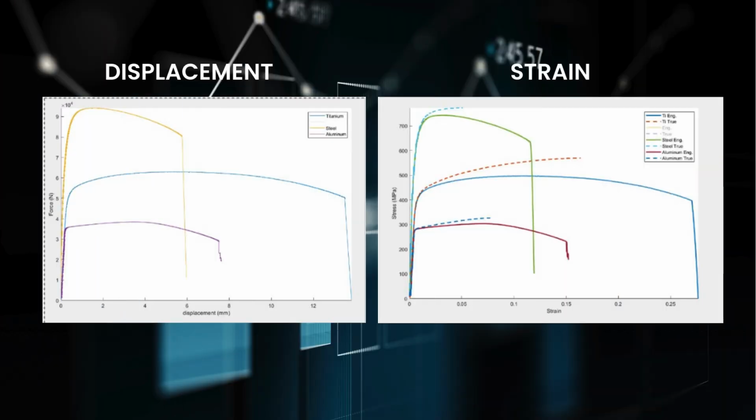Thank you, Sally. Chet Baker here to show off the graphs of the experiments conducted today. The most important one is the one on the right, the stress-strain graph. As you can see, the steel had the highest yield and ultimate tensile strength, actually being relatively close to each other. However, the elongation was just not up to par, falling a couple percent short of the standard mark.